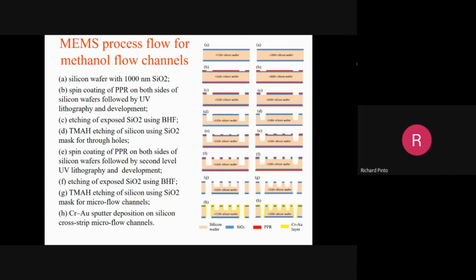So first you make the through holes. Why do you need through holes? We need to get methanol into the flow channel, so we have to make the through holes. In C, you see the E there. D is actually partially etched. D is TMAH etching of silicon using a silicon dioxide mask for through holes.